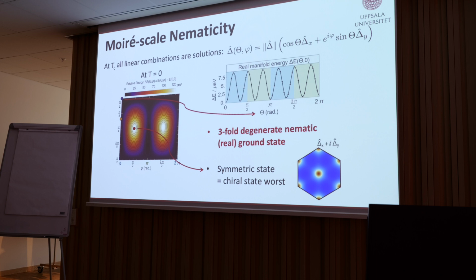What's actually interesting is if you were to take this state here, that is the worst state, this is the perfect chiral state. It's actually the state that was best in graphene that is the worst state here. And it is the symmetric state, but it has the highest energy, so this was a state that would absolutely not happen in this case. So that was the Moiré scale nematicity on the whole Moiré pattern, but I have atomic scale resolution, so let's see what that gives us.